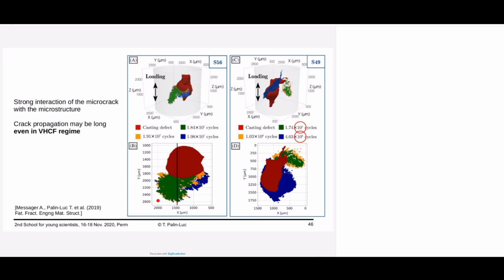So this one column, the first one, shows you a crack which was initiated after 1.8 10^7 cycles. And you can see that the crack here doesn't propagate from 1.8 10^7 cycles to 1.9 10^7. The crack was practically stopped. But after, if you continue a little bit more, up to 1.98 10^7 cycles, a secondary crack appears here. So this shows that the crack propagation can be very long, even in the gigacycle regime.